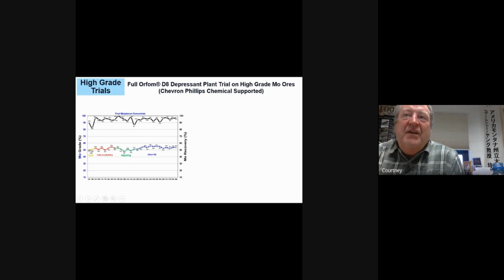They're using NaSH right here, and then they switch over to cyanide compounds, and you can see that the moly grade is a little bit better than if they weren't using NaSH but using cyanide instead. And then they're going to switch over to Orfom D8. Now there's a learning curve in here, and that's why they say this adjusting. And as soon as the operators get used to using this compound, you can see that the moly grade starts to improve just a little bit, but it's definitely better than NaSH and slightly better than the cyanide compounds.